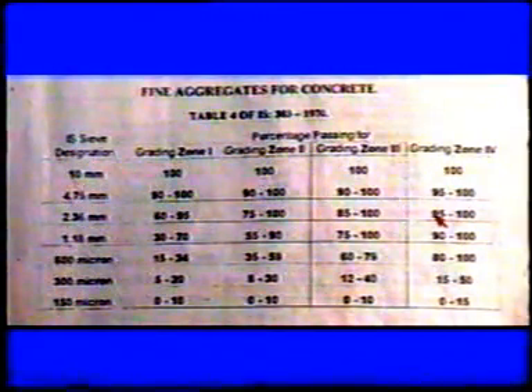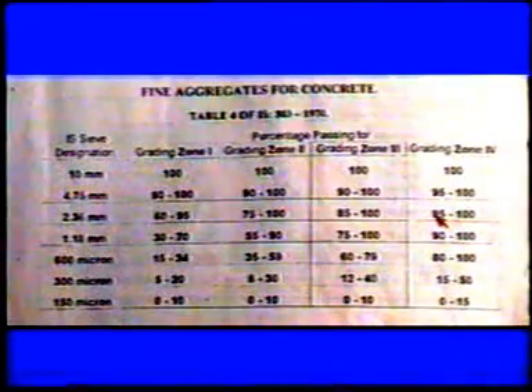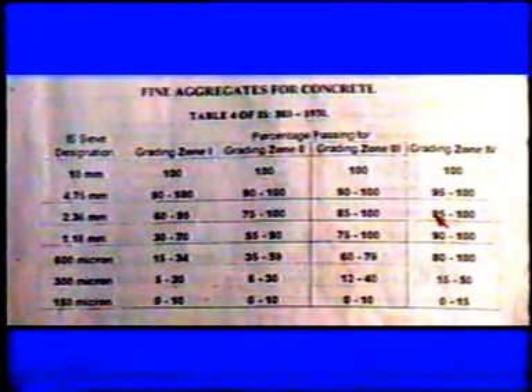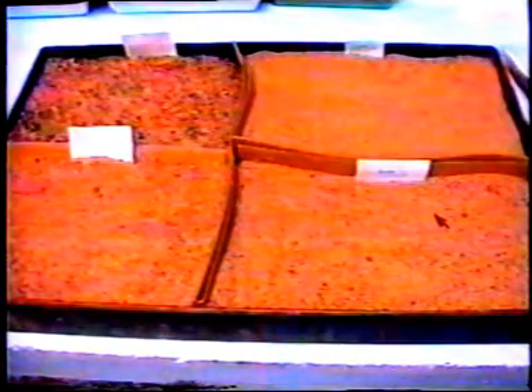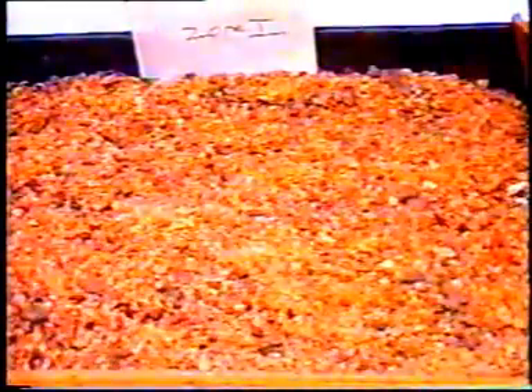Now let us have a look at the fine aggregates of Zone 1, Zone 2, Zone 3, Zone 4. This is sand of Zone 1 grading. This is a coarser one with a fineness modulus of nearly 3.5. This is Zone 2 graded fine aggregate. This is most ideal to use in the concreting purposes. Its fineness modulus ranges from 2.8 to 3.2.